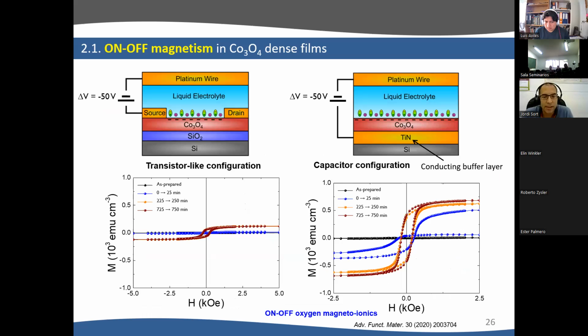Then what we also did is to compare what happens if you use the capacitor configuration that I was explaining at the beginning, where basically you grow cobalt oxide on top of a conducting layer. This case is titanium nitride, it's conductive like copper. And then you have a large effect, as I've shown you in the previous slides, or the transistor-like configuration where you grow the layer on top of silica, and then you induce the effect laterally, and it's smaller, but it is there. This we did because some people for magneto-ionics use the transistor-like configuration, some others capacitor-like, and well, the capacitor works better, as you can see here.